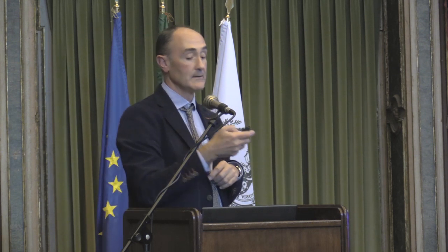So now, in order to try to understand how these small crystals grow, you need to at least try to follow some of the classical theories telling you how particles can evolve in solution depending on the concentration of the precursors and how fast the reaction goes. And so what we normally try to do is we try to separate the processes of nucleation from growth so that we can actually somehow affect the growth on well-defined seeds. And also to avoid that seeds are formed continuously during the reaction, which would lead to this very disparate distribution of particle sizes. So once we know this, we can actually go and use something similar to what Professor Mingos was showing to make his very small clusters, using a very strong reducing agent to reduce gold chloride into tiny particles that then we use as seeds to grow the larger particles that we need.